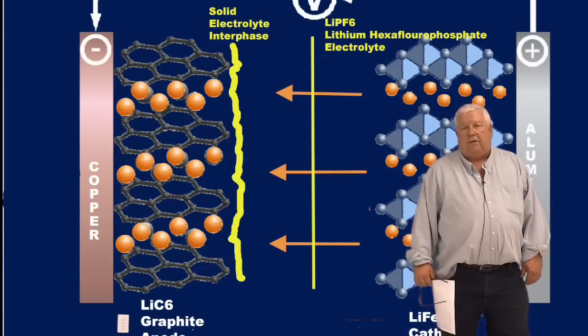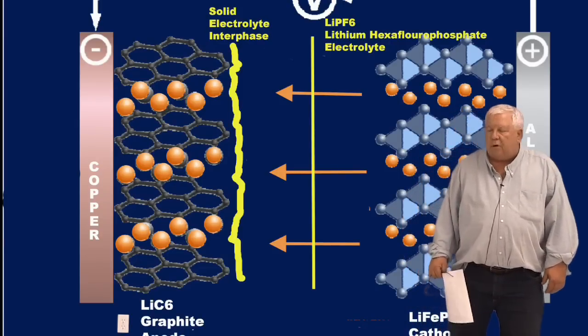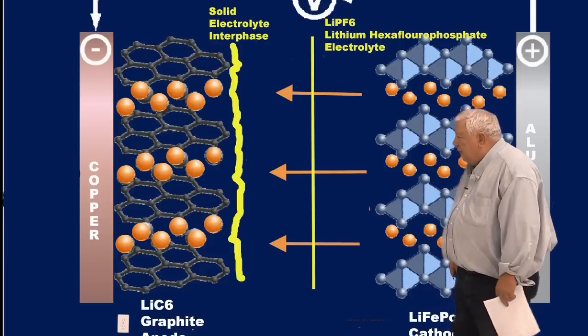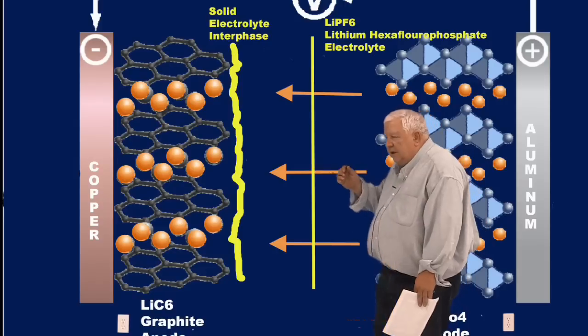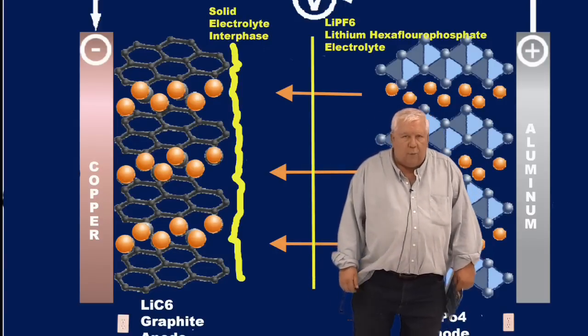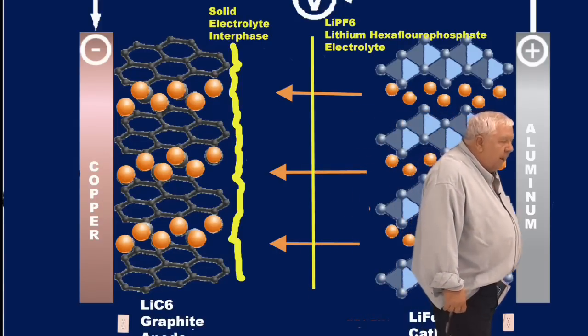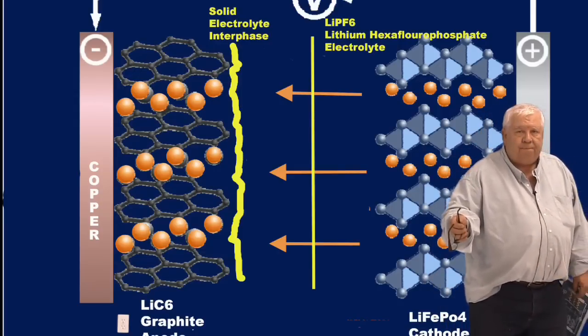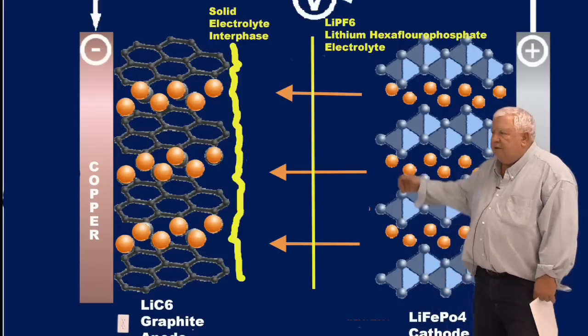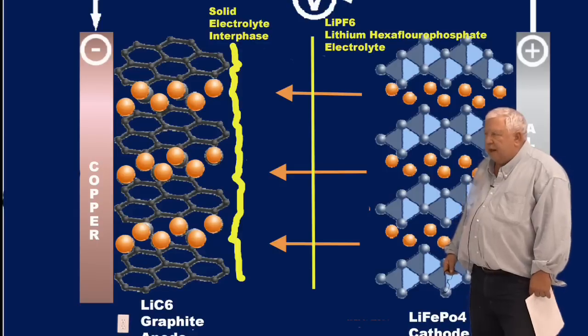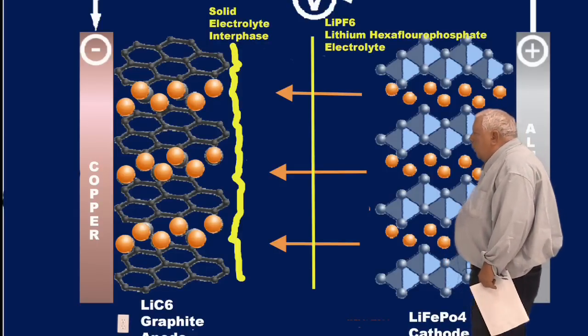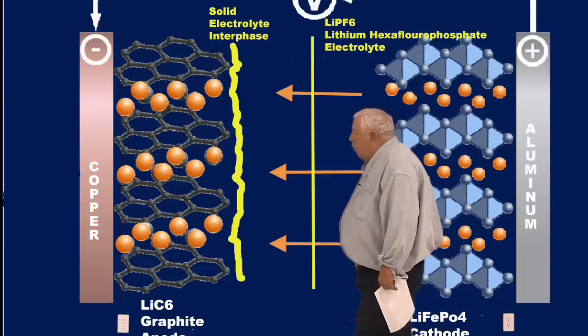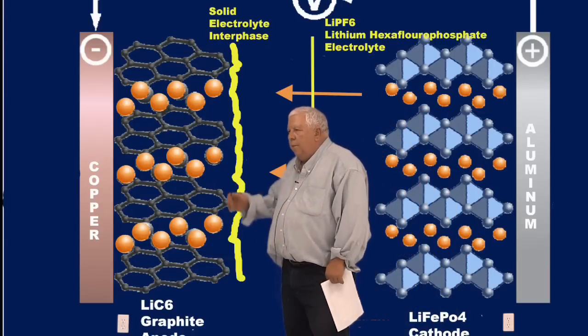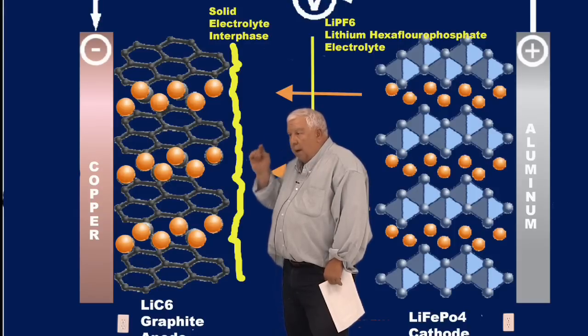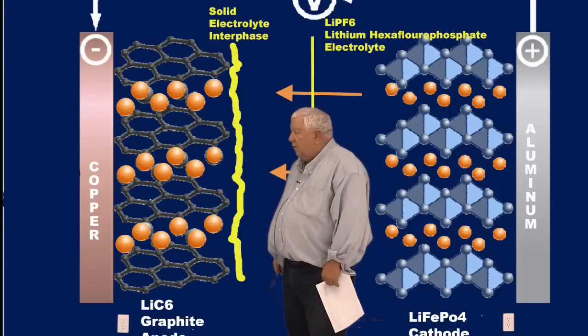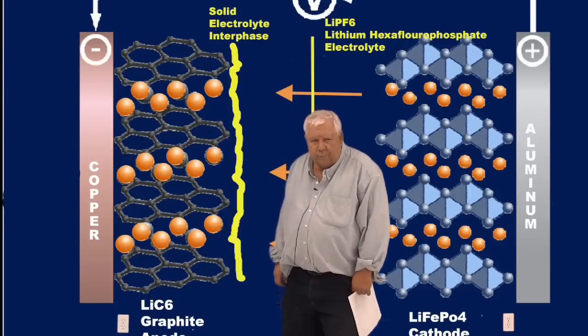Let's talk about over-discharge and how that's all better, because it can burn your car down too. We actually recently had our first experience of an over-discharge causing a fire, and it was with an A123 battery that we over-discharged and then let sit for 6 days. And on the 6th day, it burst into flames, burnt 1.5 inches through a 2-inch maple tabletop, filled our shop with smoke, and was really quite a thermal event. So be aware that it is now dead certain that over-discharge can also cause a thermal event.